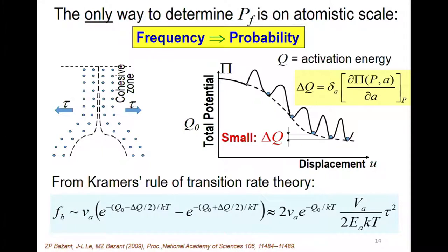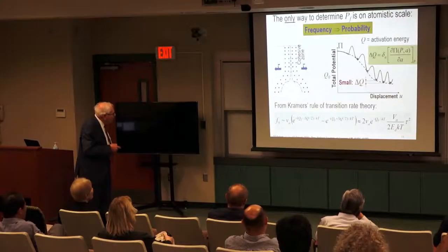You might object, what about impact? It goes very fast, right? In impact of a missile into a bunker, you break atomic bonds at a frequency of 10 to the power 9 per second. But there are 10 to the power 14 thermal vibrations, random vibrations, per second. So on average, how many times do atoms vibrate? 14 minus 9 is 5. They vibrate 10 to the power 5 times, 100,000 times, and then there's this jump. Then the bond is lost. So that's quasi-stationary, so probability is exactly equal to frequency. That's the only scheme. So we looked, that was a decade ago, at the propagation of a crack through an atomic lattice.